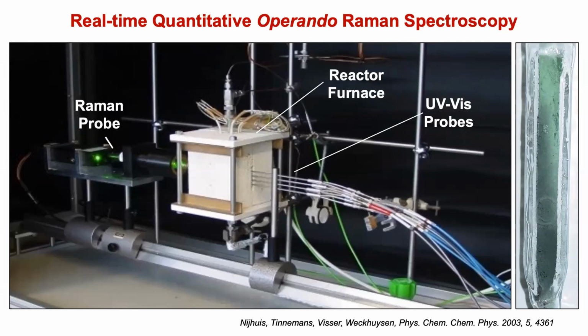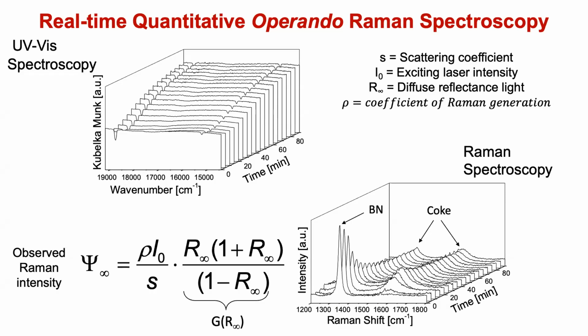But if you do that, you want to quantify, because what do you want to know? In this propane dehydrogenation reactor, or alkane dehydrogenation reactor in general, you form coke. Coke deposits, and after a while, the active sites are covered by coke and you want to burn it off. So you want to measure the amount. How can you do that? Long story short, this is an equation, you have to believe me now, with which you can correlate Raman and the darkening. If a catalyst gets blacker and blacker or less colorful: chromium 6 is yellowish orange, chromium 3 is green. So it means that you see a color change when it is darkening with coke deposits.